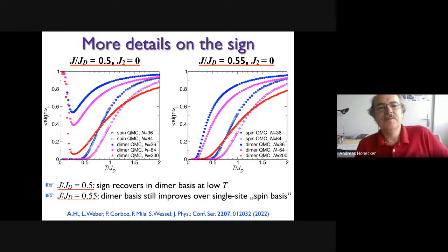Now, here is another perspective on the same kind of thing, by focusing here on the case of a ratio 0.5 of the couplings, the Shastry-Sutherland model, and on the right 0.55. In both cases you have open symbols that show you the single spin basis, the one that I discussed before, and the full symbols show you the average sign in the dimer basis. And you see that for a given system size, the dimer basis is always better than the single spin basis.